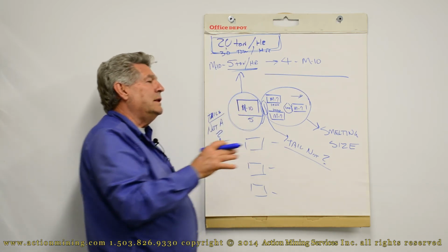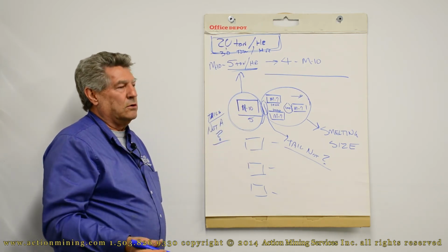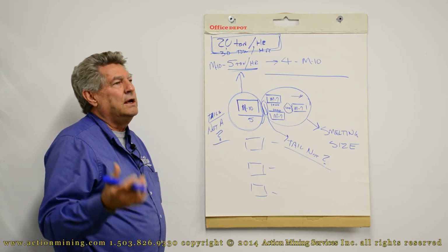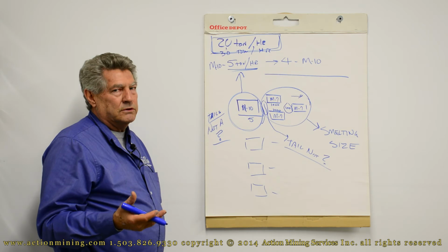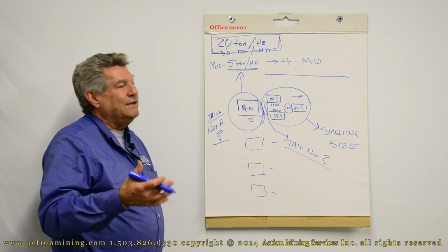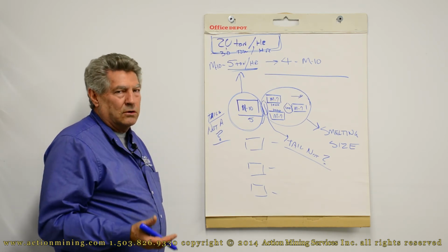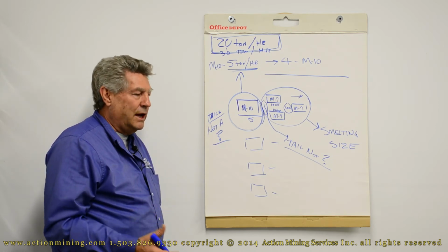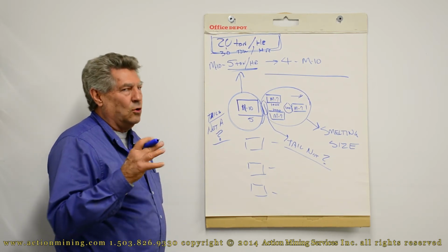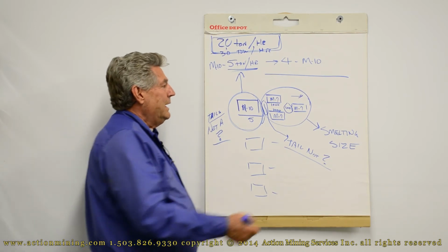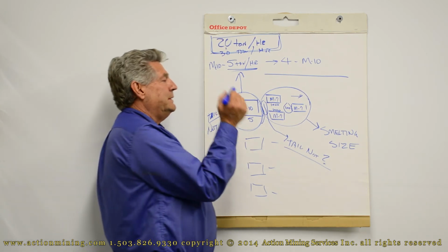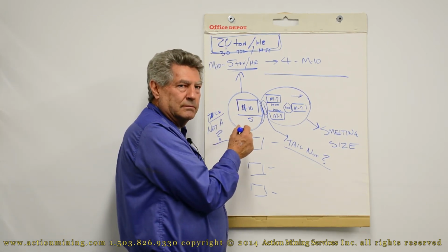Now, when I say that, I'm talking about recoverable gold. I'm talking about gold that's in particle size, or either that or tied up with your sulfides. If it is soluble gold, gold chlorides, gold oxides, any of the fancy golds that you can have out there, if they don't gravity separate, the table's not going to catch them.